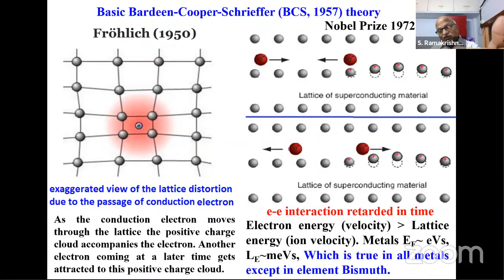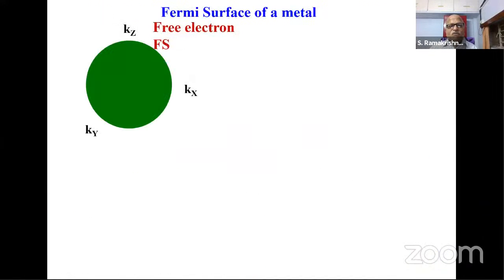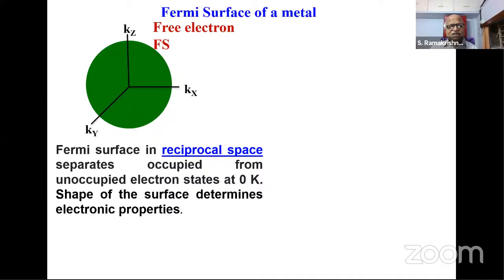This works correctly for almost all metals, but not in the case of bismuth. In bismuth, because the carrier concentrations are small, the Fermi energy is much, much smaller than the lattice energy. So if bismuth is found to be superconducting, BCS theory cannot explain this. It is not meant for bismuth. We will look into this a little more. So this is the basic thing.